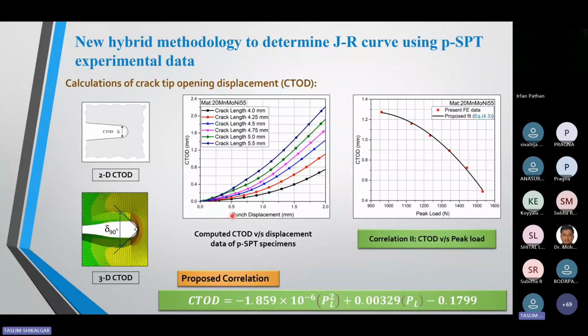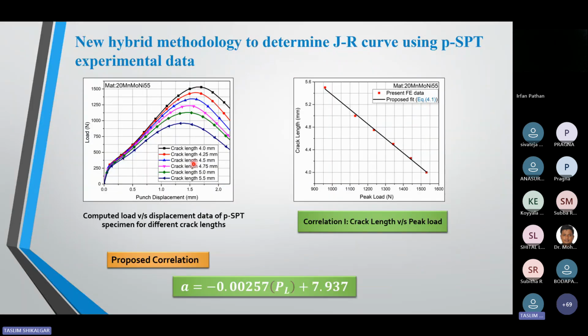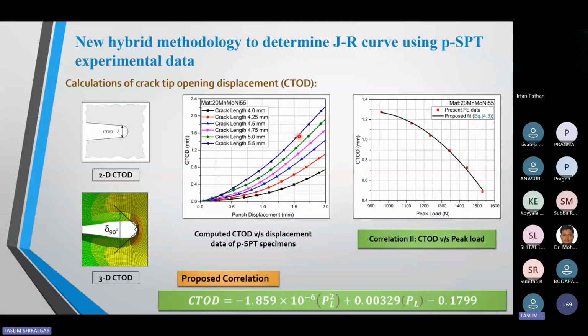And from this, at a peak load, how much is the CTOD? I calculated like this. From this peak load, I am getting this punch displacement data. And for that respective punch displacement, how much is the CTOD? So based on this data, I again generated one correlation that is known as the CTOD versus peak load correlation. And this is my second correlation.